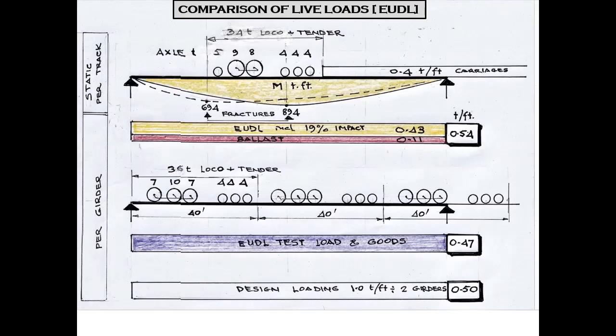I've tried to compare the loadings here. At the top you see the train in the position which would have caused the maximum bending moment to mid-span. And you can see as the train approached the quarter span, it produces a bending moment, obviously a little lower, but somewhat higher than if it was a UDL. And this may have caused the second of the two fractures in the girder. That's a bit conjectural. Now, the UDL of the train, equivalent uniformly distributed loading, including impact, which I've allowed 19%, I've allowed some impact due to structural interaction, some rail joint effect, and a bit of lurching from steam locomotives.